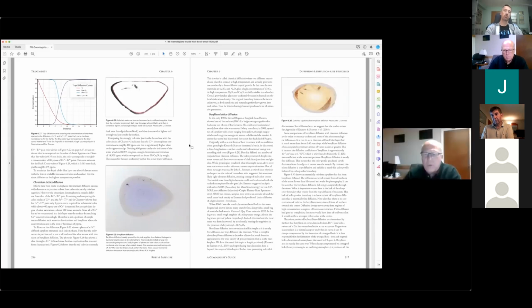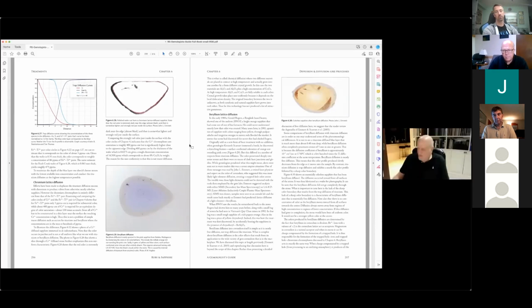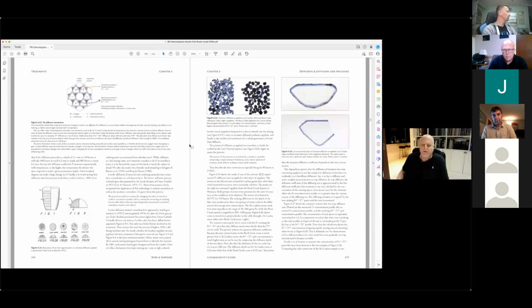Beryllium. Just a quick question, if you don't mind. The diffusion process, is it done on cut stones, on rough, and how deep into the stone does diffusion actually progress from the surface? Okay, so for titanium diffusion, the depth is very shallow. You can't get much penetration because the titanium ion is too big. But beryllium is a very light element, and so with beryllium, you can diffuse it deeper into the stone, and if you heat the stone long enough, you can diffuse it all the way through a cut stone.